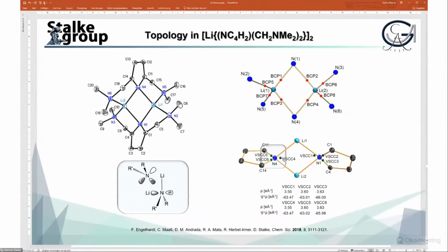So if we look at that in terms of rabbit ears, that would mean we have sp2 hybridized nitrogens, and the one is standing orthogonal on the lithium-lithium vector, meaning this VSCC points to both lithiums, addressing the two of them. So that, of course, is the environment for this one. This would mean this is parallel to the 4-membered ring, and this one is more or less orthogonal to the ring, meaning we have to address both bonding scenarios.